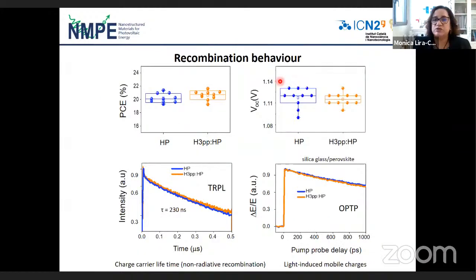Then we also observed, you can see here the voltage again, but we made many analyses on the as-prepared materials and also the devices, and we observed in every case, in any case, we always obtain the same properties. The as-prepared materials were both the same. With and without the additive, at the optimized amount, we didn't obtain any improvement.